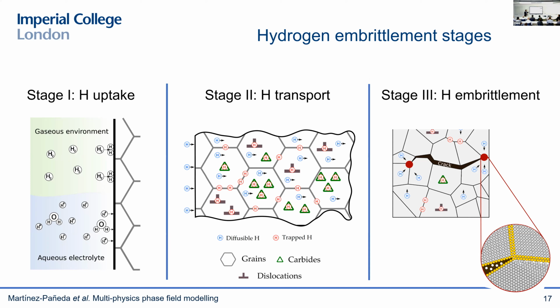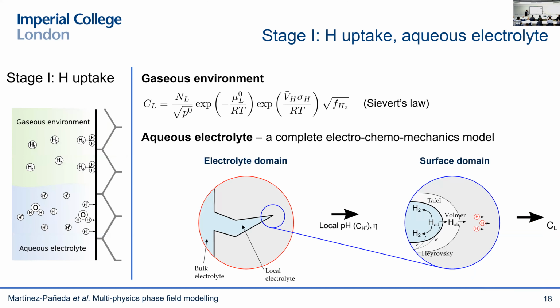And to me, the key was to try to resolve all the physical processes involved. So only by taking a kind of a physically based mechanistic point of view, I was able to be confident in my predictions and be able to extrapolate on what's going to happen. So I tried to resolve the physics involved in the hydrogen uptake process, the ingress of hydrogen, in the transport of hydrogen within the metal, and also in the fracture process itself, in the breaking, the accumulation of hydrogen at critical interfaces, and the nucleation and growth effects. So let me tell you a little bit about it.